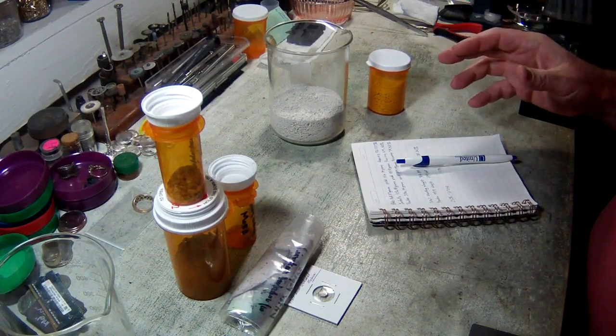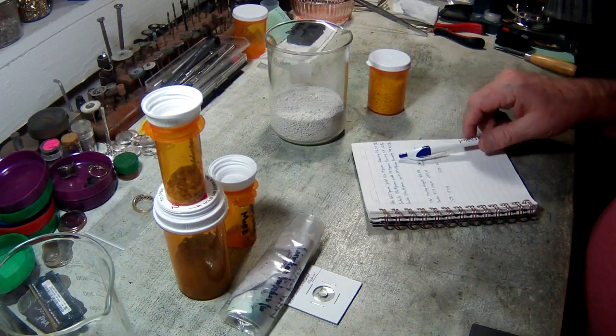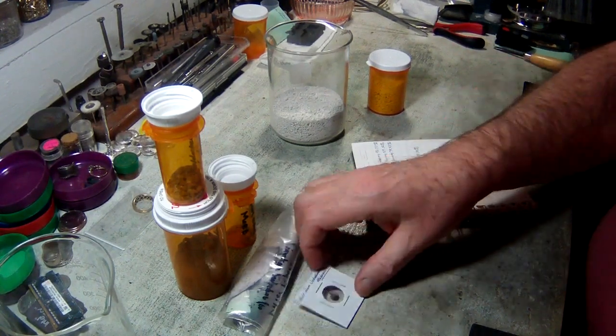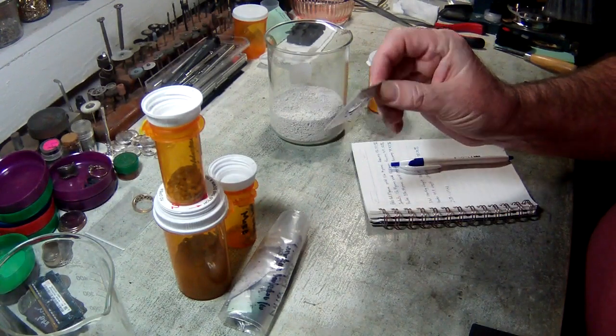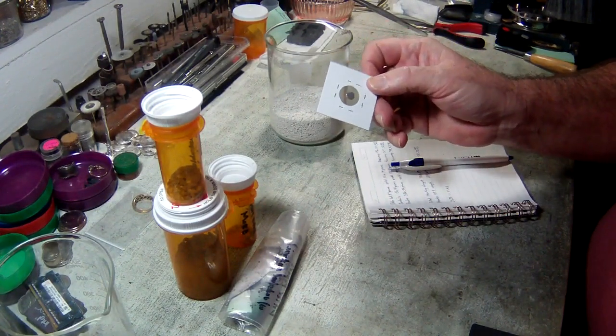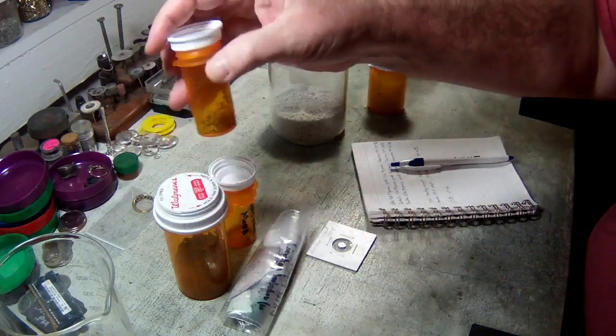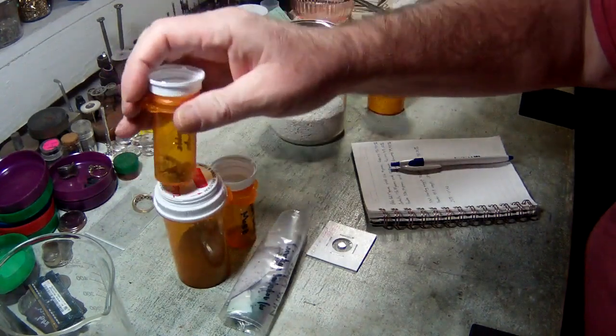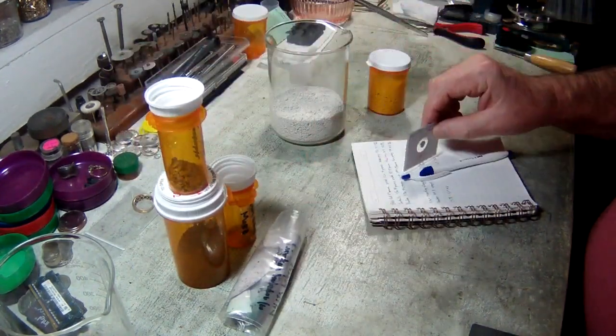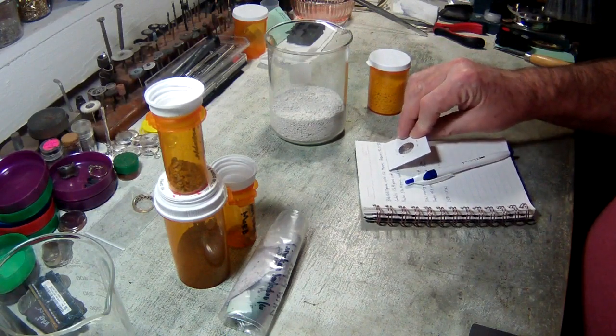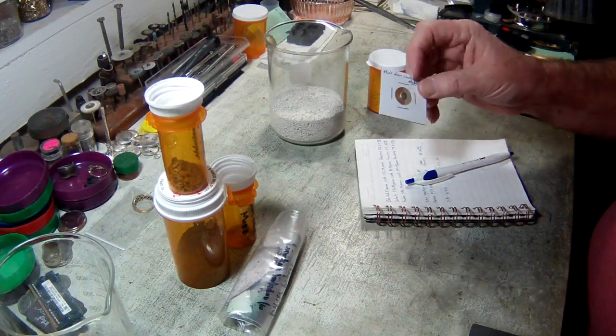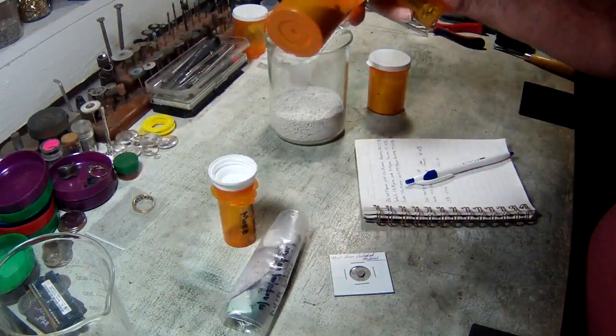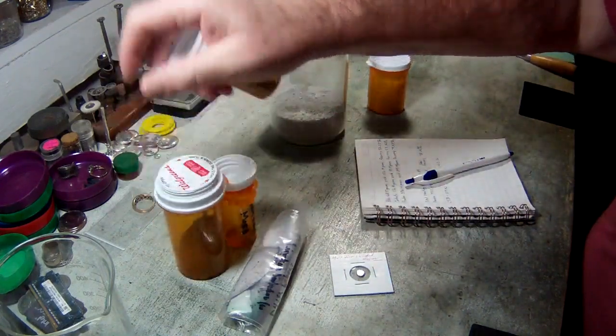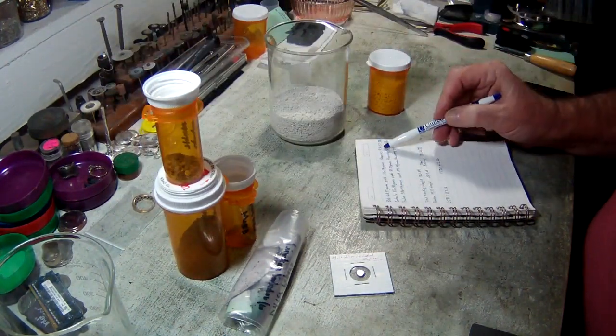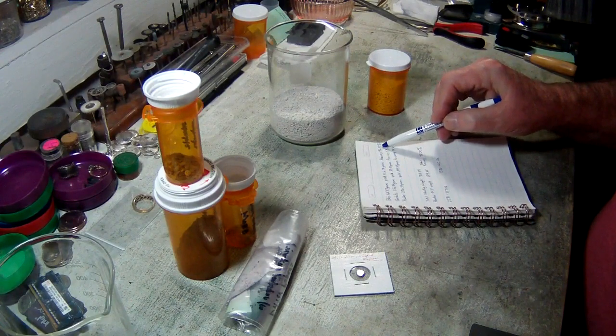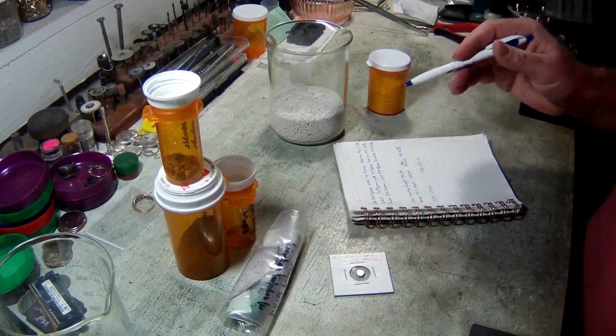Now the reason we got so much from that blob, and so much more than we got from the powder that we tested, is that when I melted this, this is actually only about half of what I put in the dish to melt. Whatever else is in these powders just vaporized, so that was quite a bit of weight gone. Since I had started melting that blob down, I burned off a lot of this material. So the blob was a heck of a lot purer than the powder was. It was actually 92.57% pure. So the blob ended up being our best yield.